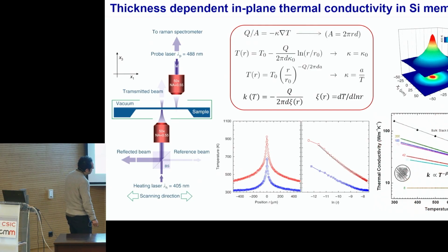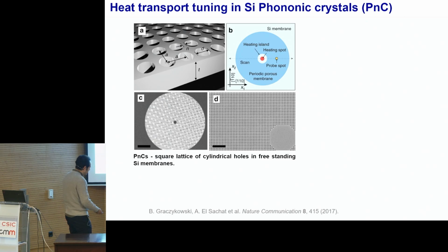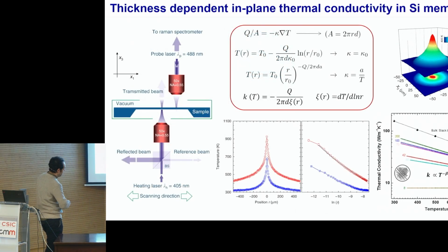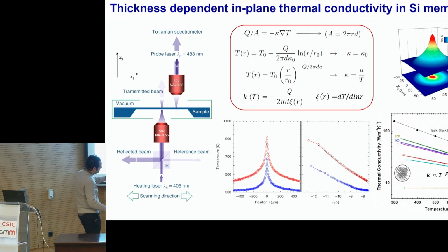On the other hand, we see that by increasing also the temperature, actually we increase the phonon umklapp scattering processes. So we have more phonon scattering in our membranes, and again we see this trend of decreasing the thermal conductivity.